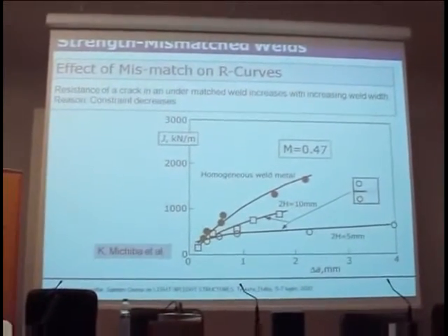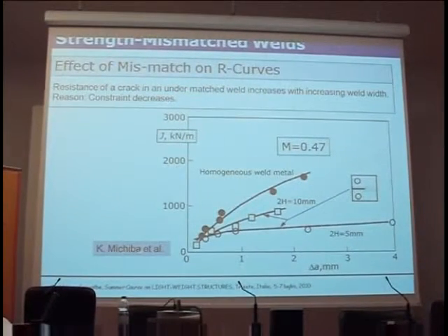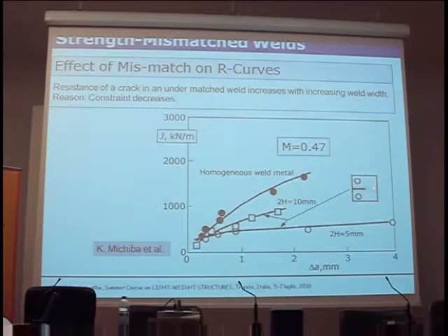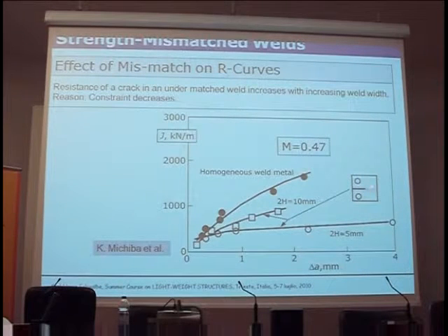Now, this is another interesting example. This is Japanese work by Michiba. He did R curves in terms of the J integral, and on CT specimens, three different CT specimens. He made a CT specimen completely out of the weld metal here. And this is the R curve. And then he had a specimen with base plate and the same weld metal with a height here of 10